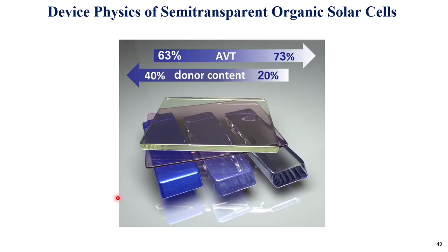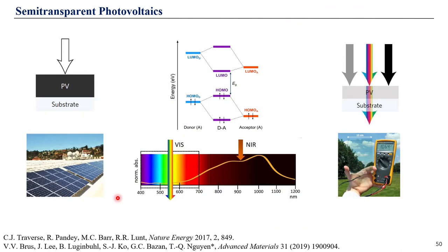So the next project is based on device physics of semi-transparent organic solar cells. We are accustomed that solar cells are supposed to absorb all light and convert it into electricity, and that's why usually solar cells are opaque devices. However, for some purposes in integration needs, we require semi-transparent solar cells. And that could be achieved with conventional inorganic semiconductors only by thinning the active layer. However, in that case, the solar cell becomes semi-transparent not only in the visible spectral range where human eyes can see, but also in the UV and near IR spectral range, which significantly limits their performance.